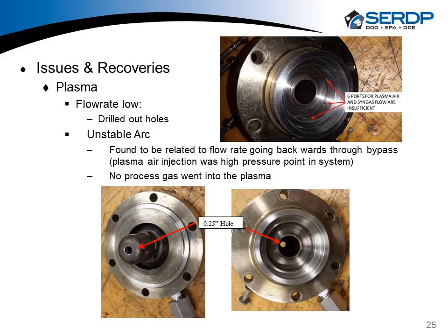And then the danger was an unstable arc. We didn't want to remelt that plasma, or I'm sorry, the ceramic insulator or anything else. So we were kind of gun shy on running the thing to the full potential. And what we found is that the air injection was the high pressure point in the system for some of the plasma runs, and as a result, we didn't really get process gas to the plasma. It was flowing backwards towards the venturi and the other way around to the venturi. So no process gas got there in some of the experiments.